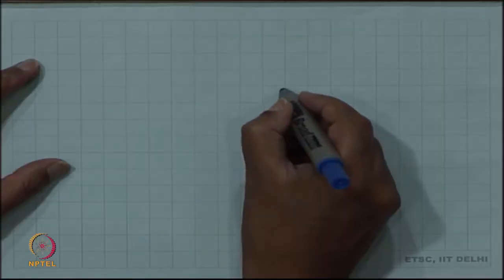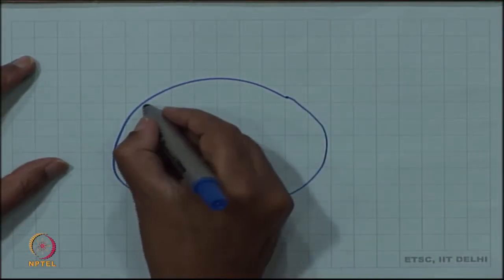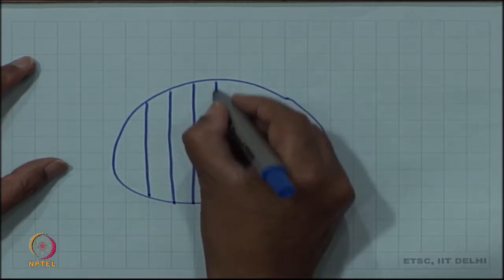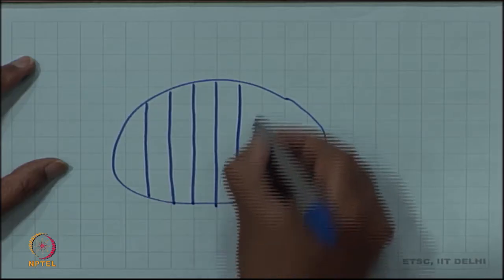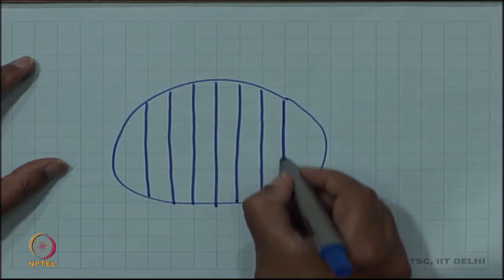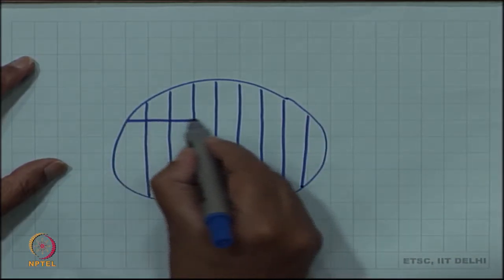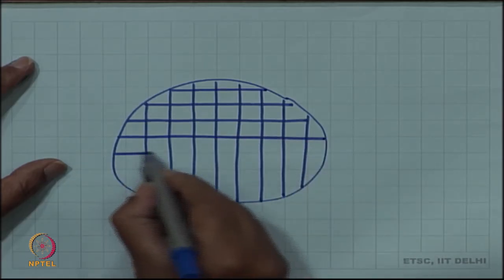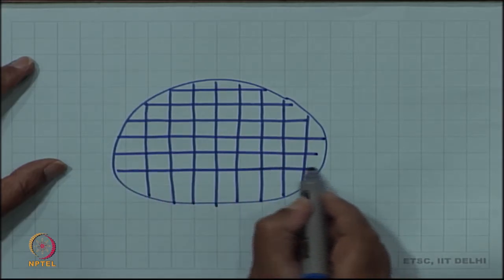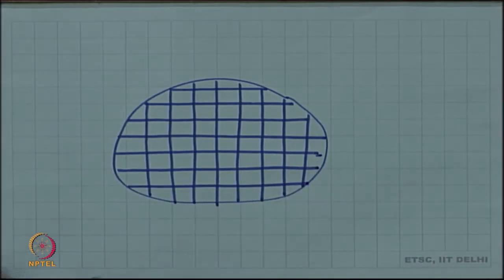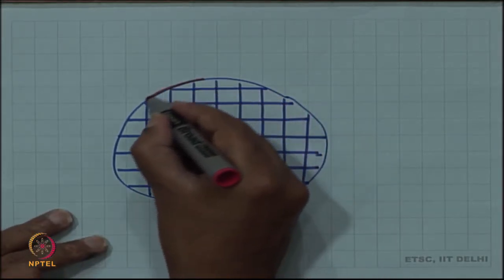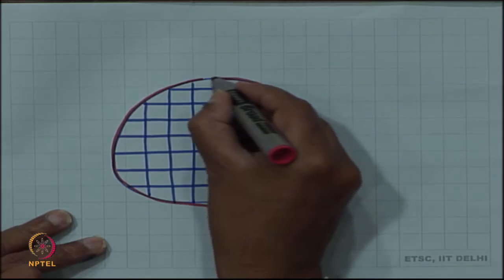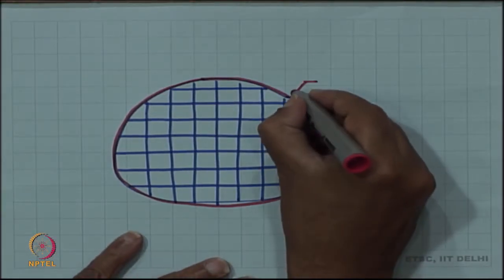If we have any crystal bounded by a surface, inside we can have a nice perfect lattice. Even if it is free, it cannot be free of vacancies at a finite temperature greater than absolute zero, because vacancies are in thermodynamic equilibrium in a crystal. But if we say it is free of vacancies and dislocations, still since it cannot be infinite there will obviously be an external boundary, and that external boundary itself breaks the lattice periodicity. So this free surface is a defect.